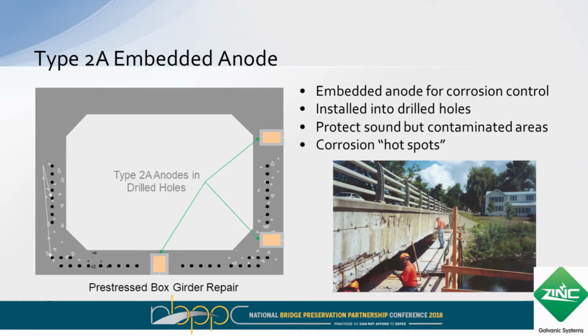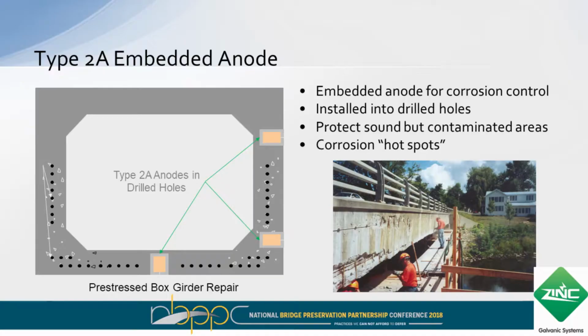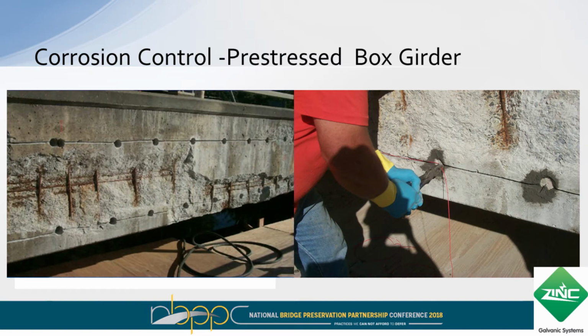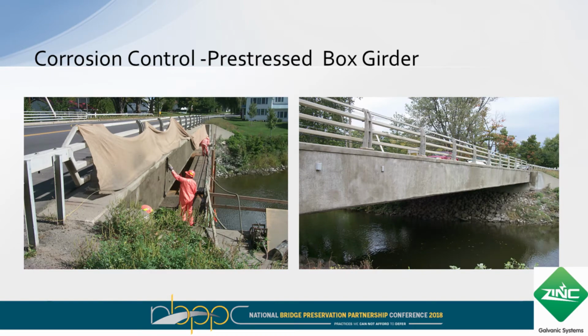So in that case, they looked at using the Type 2 corrosion control anode placed along the outside face where the drainage was, and then one underneath as well. And you see the pattern of the galvanic anodes, the interconnecting header wire. Some of the anodes were placed in sound concrete, some of them went through the repair areas, but two continuous rows across the face. And then the shotcrete repair was completed, and that stayed in place until a later time when they had the capability to replace the beam. So kind of a targeted protection to a specific area.